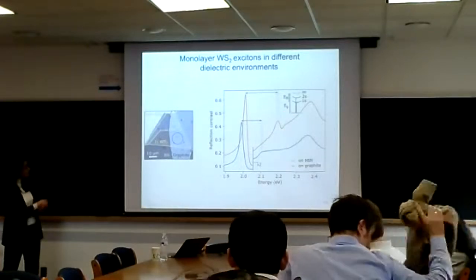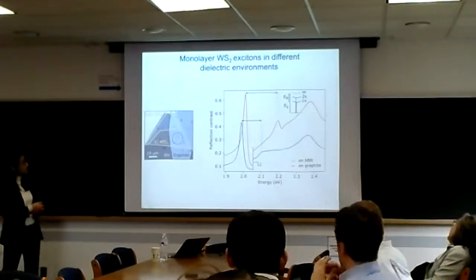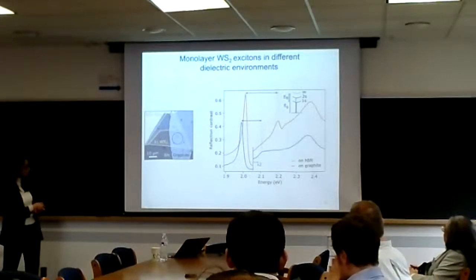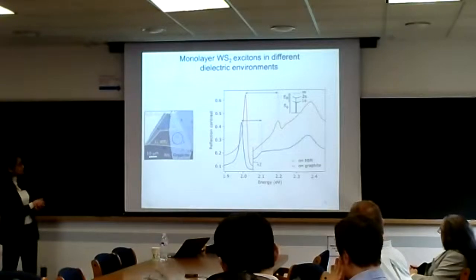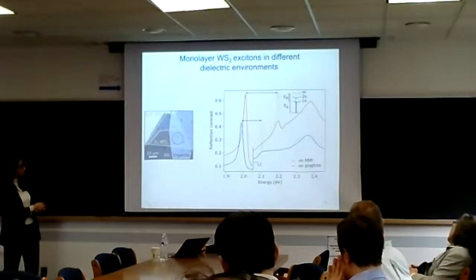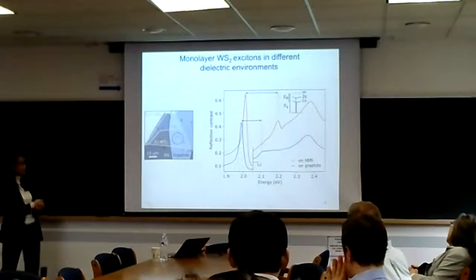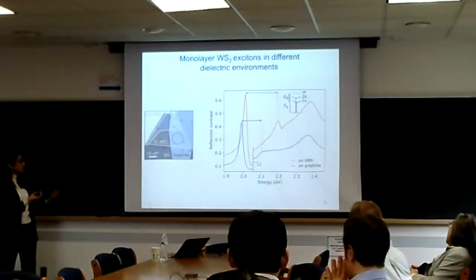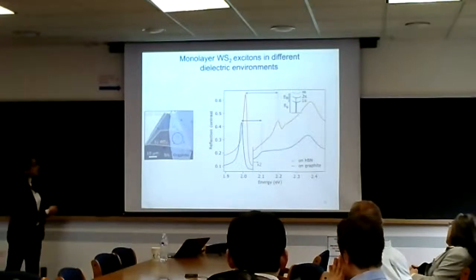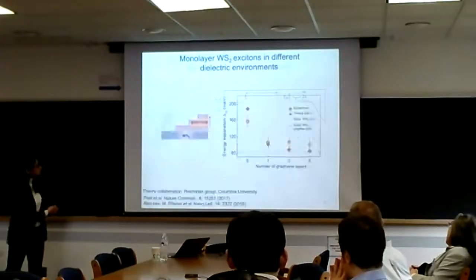and as you move the spot from this part of the sample to here, and you measure the reflectance spectrum on graphite, what you observe is that this delta 1,2 reduces, and also there's a little bit of a change in the 1s state, but a greater change in this delta 1,2. And this already tells you that the nature of the excitonic states is changing, and also the band structure should be changing. The band gaps should be changing.